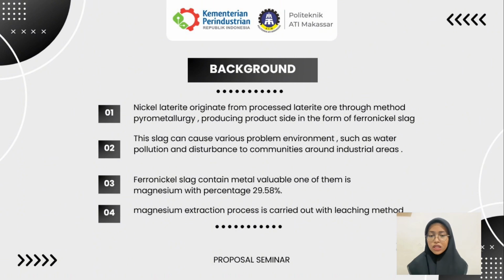This pollution can be reduced by utilizing the slag because it contains valuable metals, one of which is magnesium. Generally, the magnesium content in ferronickel slag is 29.58%. To utilize this slag, we will extract magnesium using the leaching method with sulfuric acid.